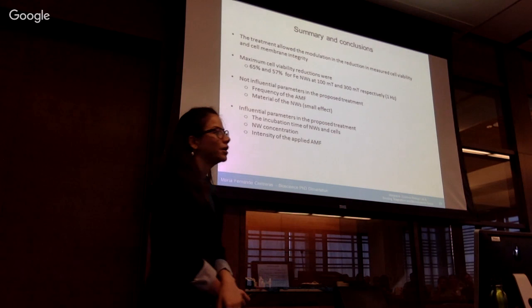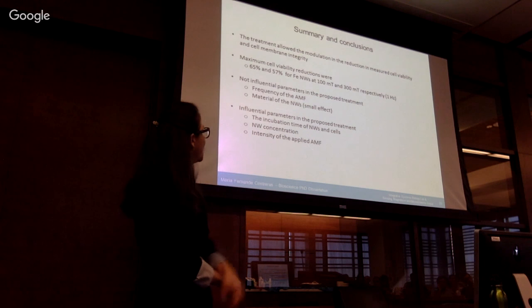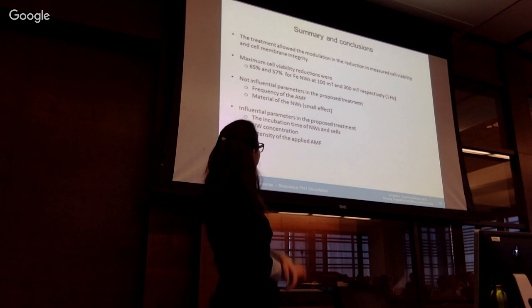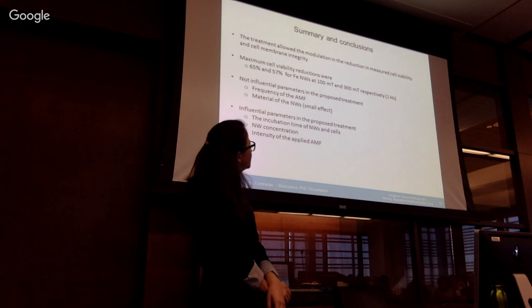And finally, what changed viability reduction when we altered the value was the incubation time of the nanowire with the cells, so the internalization process. And the nanowire concentration was very important. And finally, the intensity of the applied field determined how strong the force associated to the wire was.